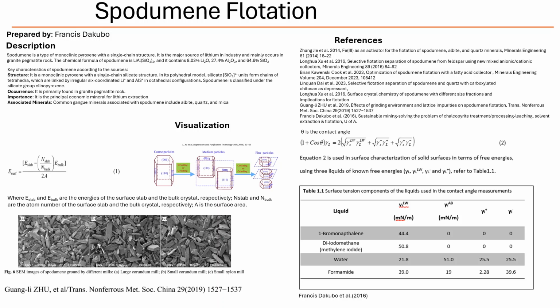So it's like baking a cake, get the ingredients and mixing wrong, and it flops. Very much like that. The studies show you generally need higher collector doses for good lithium recovery. But then you need to manage the pH carefully to keep the gangue depressed and maintain the grade or purity of the final product. And the mixing power?